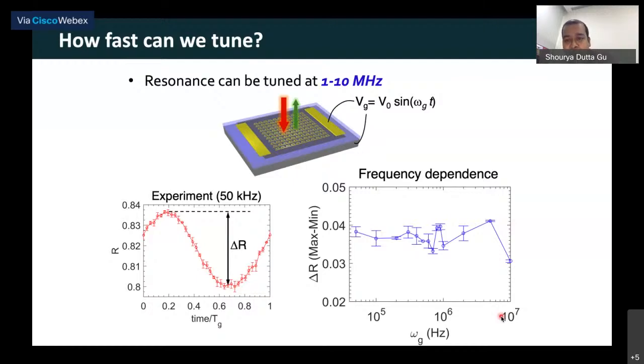So the device is responding normally. However, if you actually increase it further, go to 10 to the power 8 hertz, which we have done later, we see that the device cannot respond anymore and the signal actually reduces, right? So what you can actually do with these graphene integrated devices, as I have shown here, is that you can reduce the multiple pixels into a single pixel device, right? Which will make it much easier for a practical device application, right?